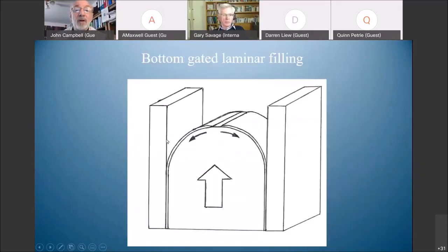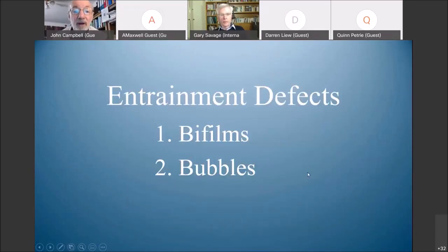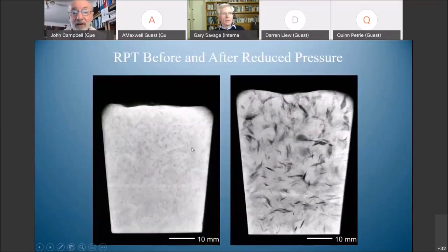And this is what we have to do if we want to avoid them. This is the way we should be filling castings. We should be gating them so they're actually filling uphill inside the mold. And then we have a chance of making a really good casting. So these are the 2 major defects, the bifilms and the bubbles. This is a little classical experiment of mine, many years old now, whereby this is first poured and solidified in air, and these tiny shadows you see are the convoluted bifilms. This is where my piece of paper has been screwed up into a little ball because turbulence has raveled the biofilm into a small defect.